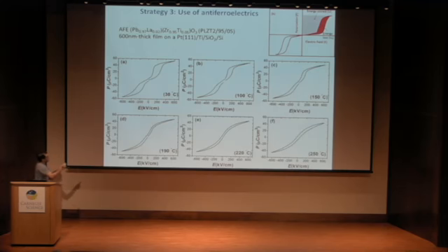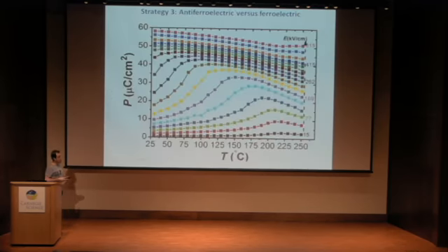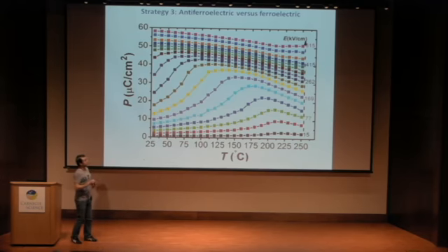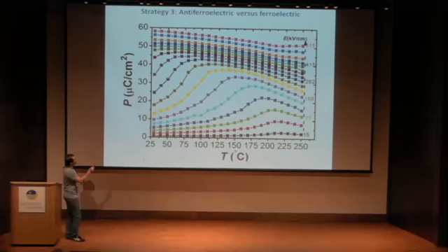And we see that, as we heat the system from antiferroelectric, we go through ferroelectric as a function of temperature. And then we can do exactly what we did before. We extract the polarization as a function of the temperature for different values of the electric field. At high electric field, you can see that we have exactly the expected shape for a classical ferroelectric system. The polarization decreases with the temperature, meaning that delta T is positive. But in the antiferroelectric part, you see that first the polarization increases, and then it decreases. So in this region, the delta T is negative.